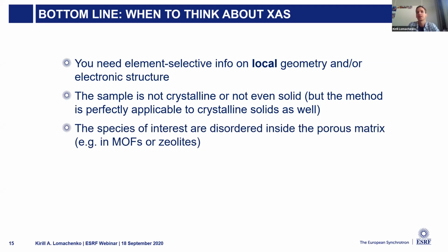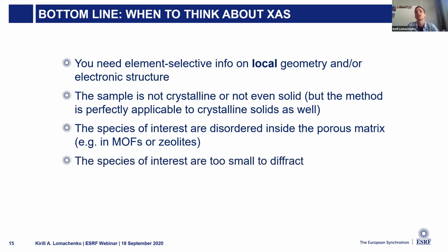When you have species of interest that are disordered in a porous crystalline matrix, like in MOFs or zeolites - these materials are very good crystals, but the thing that does the catalysis is basically isolated metal ions inside the pores - it's not very straightforward to track them with methods that are not element selective. Also, you can use these methods when the species of interest are too small to diffract. So XAS can be a method of choice.